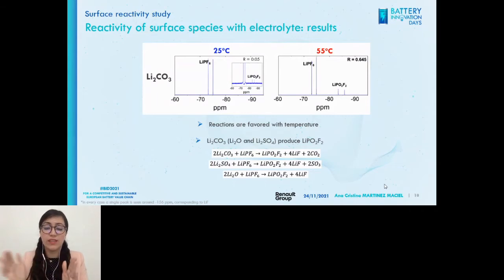We see that the production of LiPO2F2 is actually favored with temperature, because the ratio with LiPF6 is higher. So we were able to deduce that the surface species under battery conditions will react with the electrolyte, in particular with LiPF6, to produce LiPO2F2, LiF, and other gases. So we are seeing constant gas production - this is the point where we started making the relation between surface reactivity and gas production.